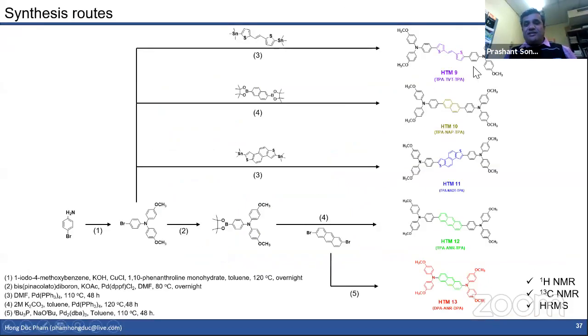And taking this central building block, we put in the same kind of end-capping group, only we tuned from a 5-membered ring to a 6-membered closed structure like naphthalene, to the more closed structure, and then somewhat longer acenes. In only the last case we put a diphenylamine, whereas in all these 4 cases we put the triphenylamine with the 3 phenyl groups on the nitrogen. Here there are 2 phenyl groups on the nitrogen, and we analyzed all of these 5 compounds.